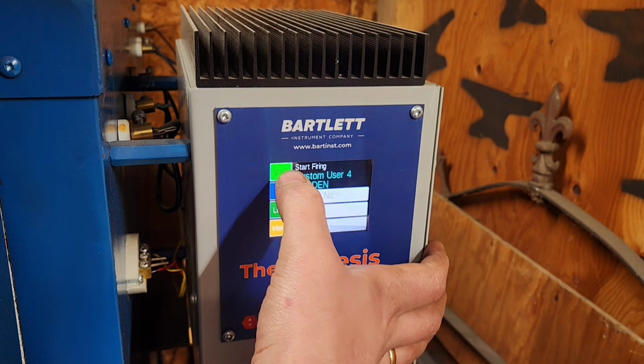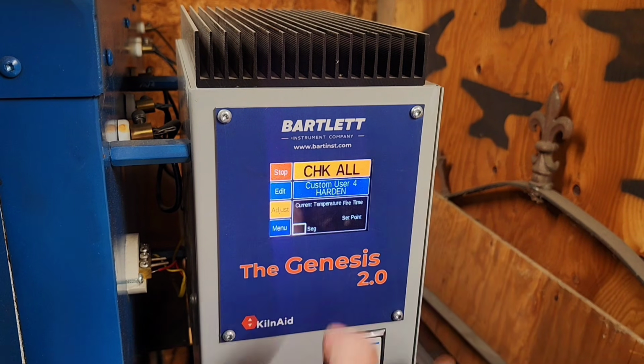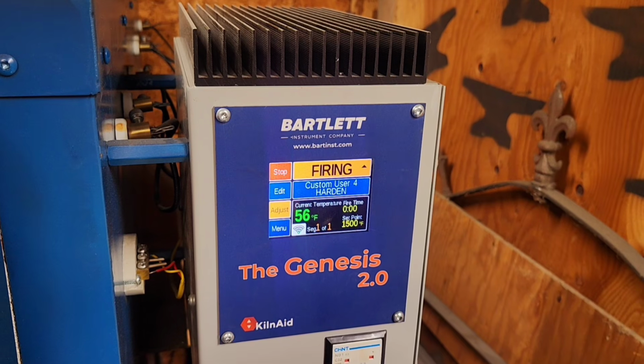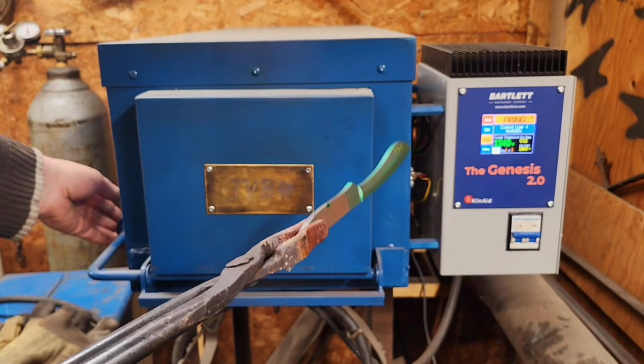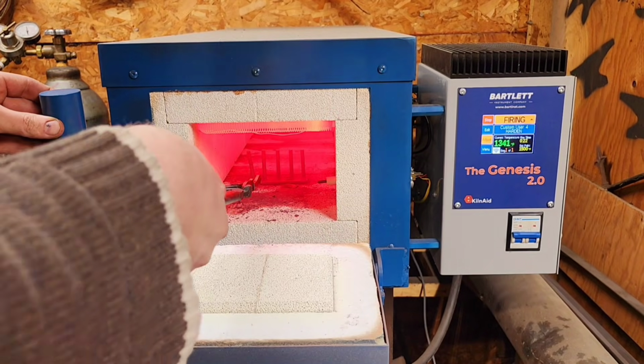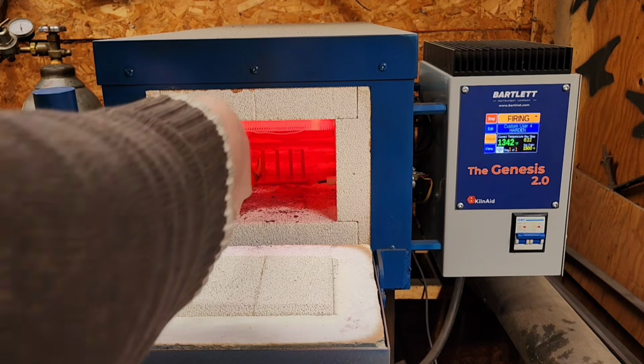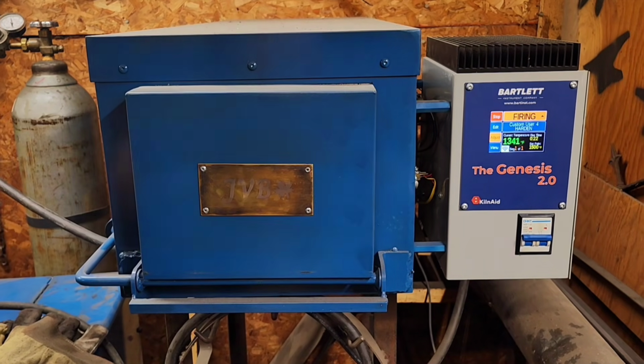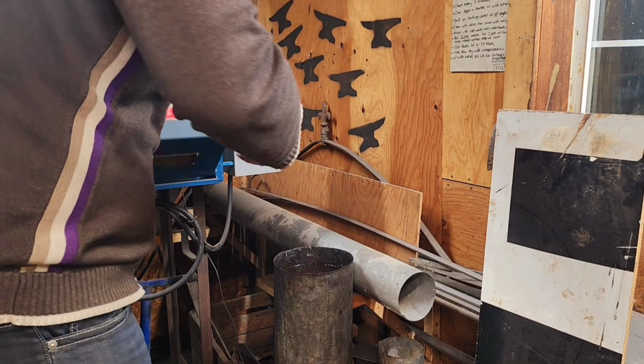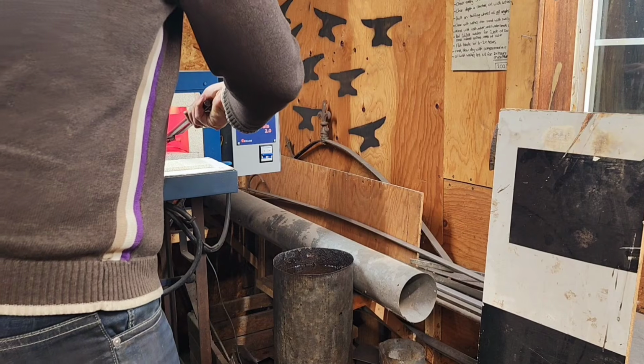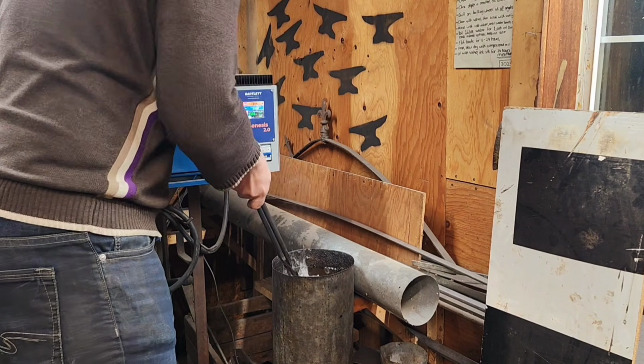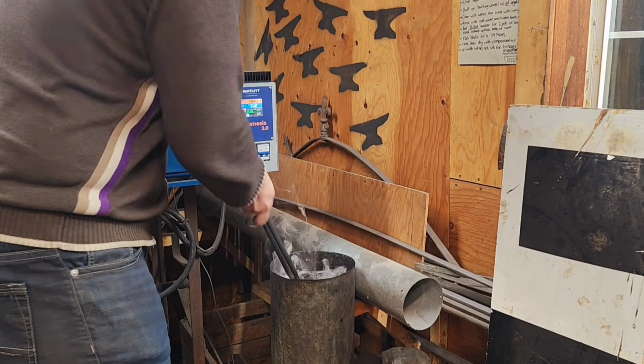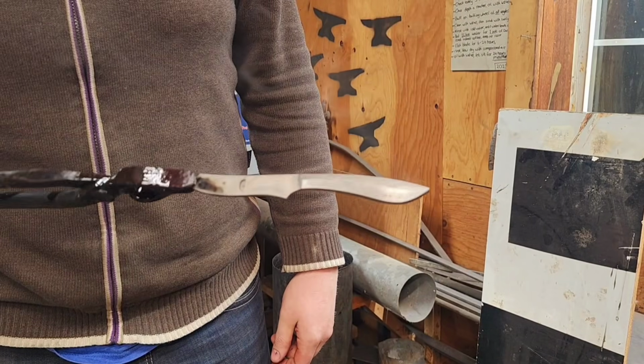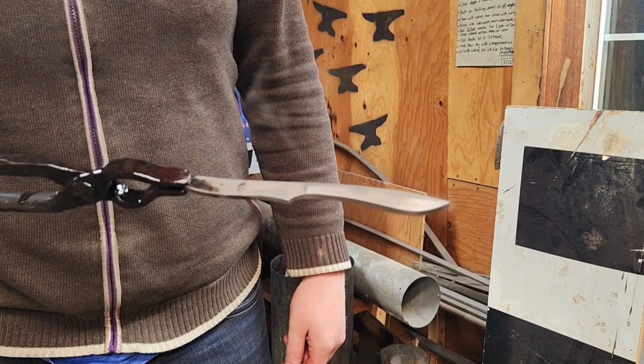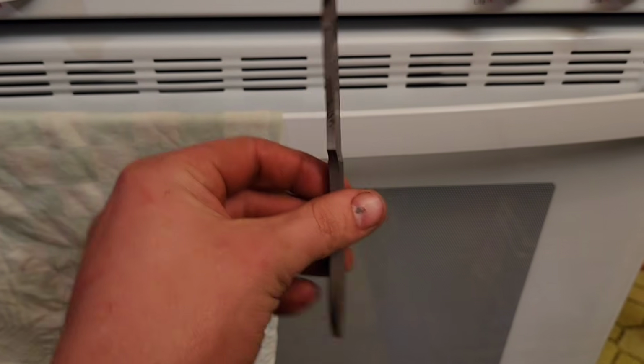Now we're going to go in for hardening. Got this giant kiln for a tiny knife, but that's alright. So we're going to set that in there and let that come up to temperature. It's going to soak there for about 10 minutes. We're going to pull it out and quench it. Here it is quenched, very hard, and ready to temper.